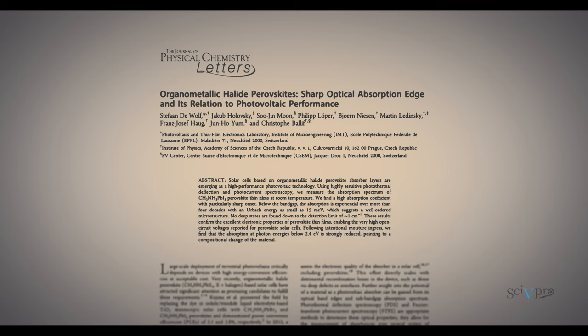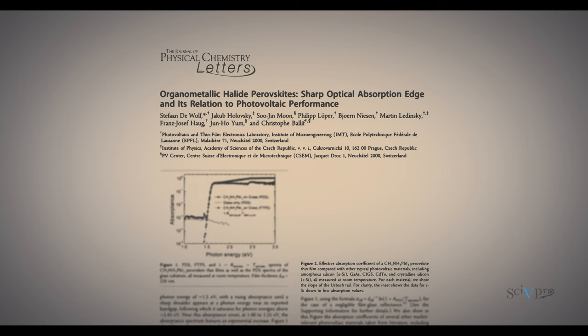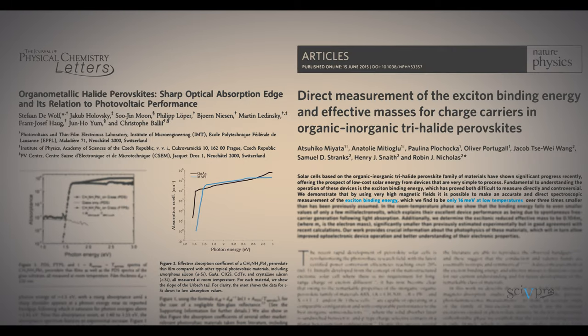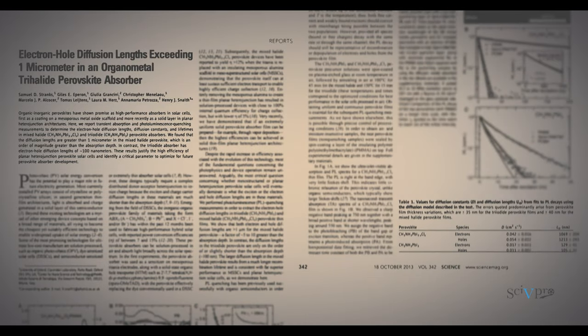However, perovskites display exceptional optoelectronic properties, which are very similar to those of gallium arsenide including strong light absorption, non-excitonic behavior, low recombination rates, long carrier lifetimes and diffusion lengths, and photon recycling.